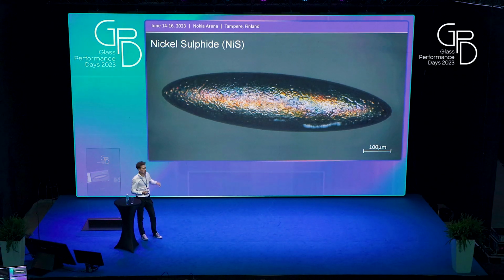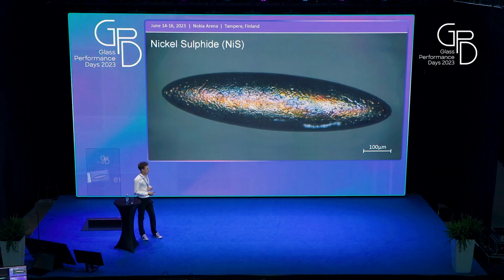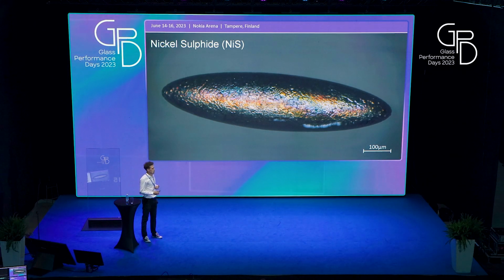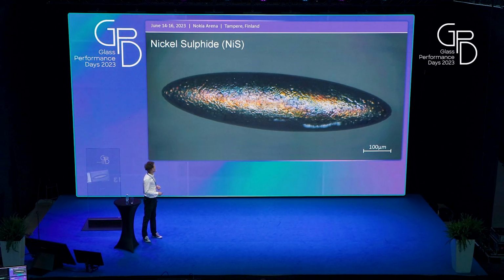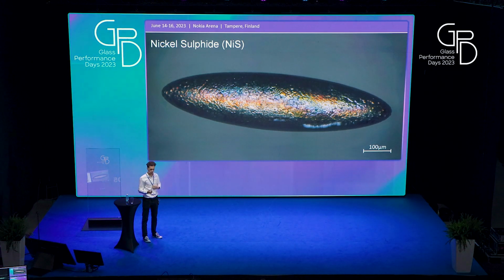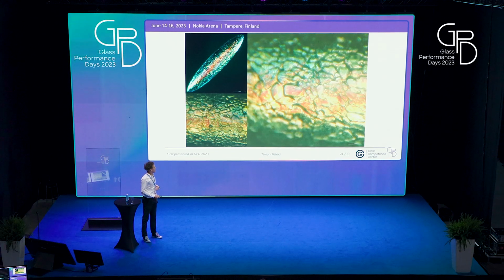First of all, you see this gold-purple color. You see it on most of the nickel sulfide inclusions, not all, but a lot of them. But what's even more characteristic for nickel sulfide is this fish scale-like surface structure that looks just like little flakes, but if you zoom in at those flakes, you can actually see that they are small crystallites that have formed.